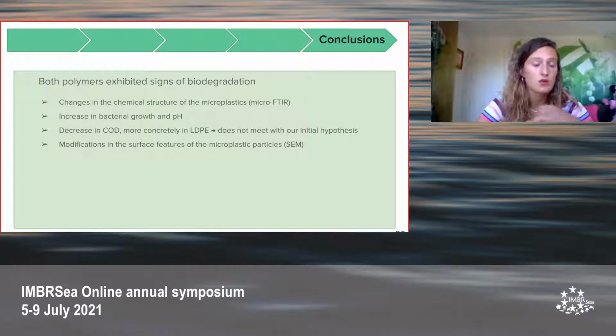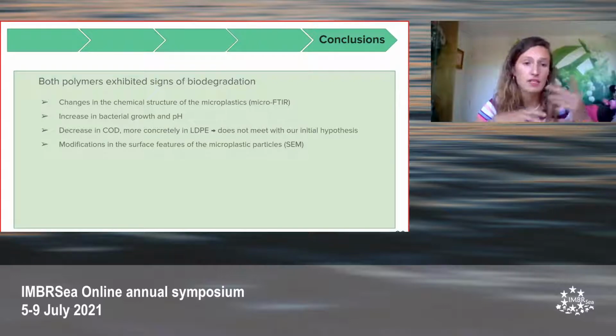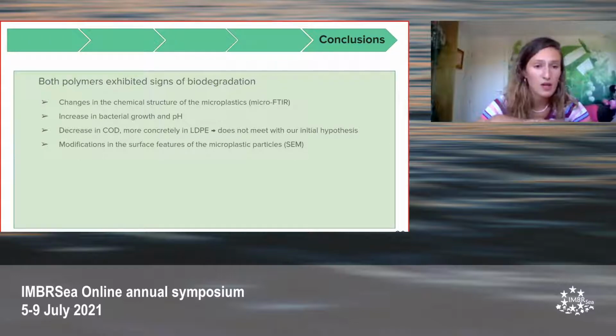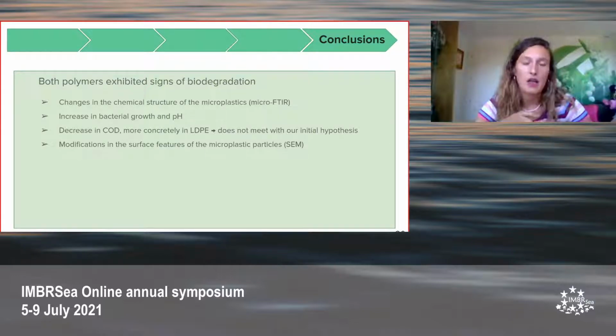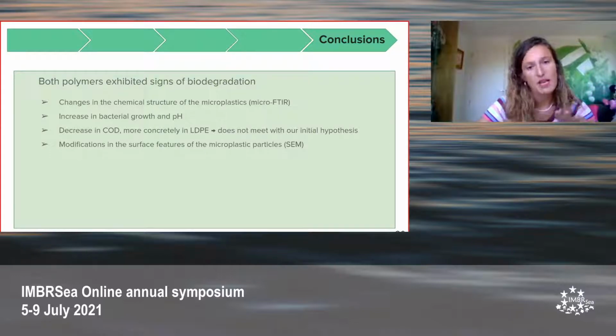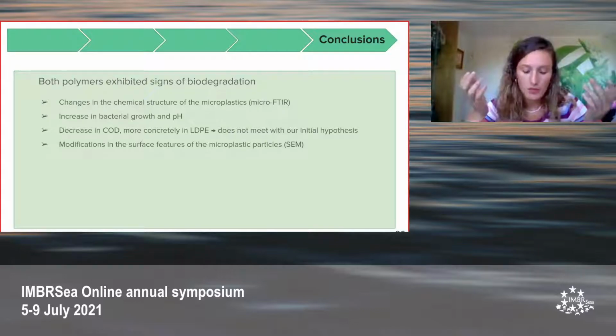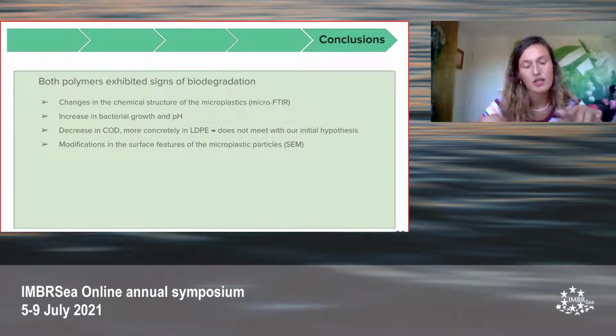in the chemical structure of the microplastic of both polymers. We saw an increase in the bacterial growth and in the pH as well, and a decrease in the chemical oxygen demand, more specifically in the low-density polyethylene particles. This does not meet our previous hypothesis, in which we were expecting the contrary, and this could indicate that maybe what is labeled as biodegradable in the end is not that biodegradable. And we also saw modifications in the surface features of both plastic polymers.